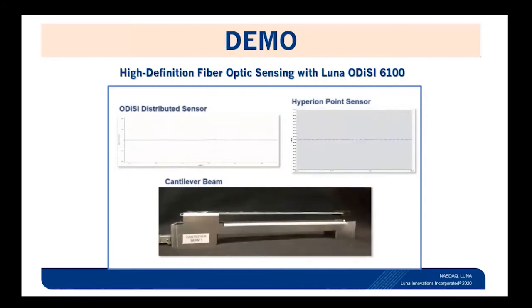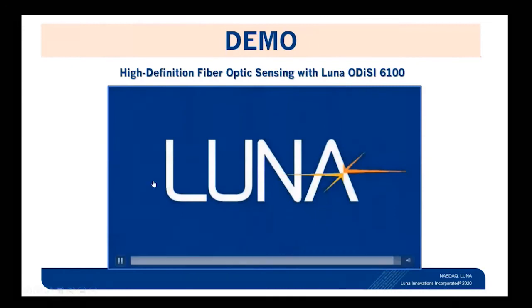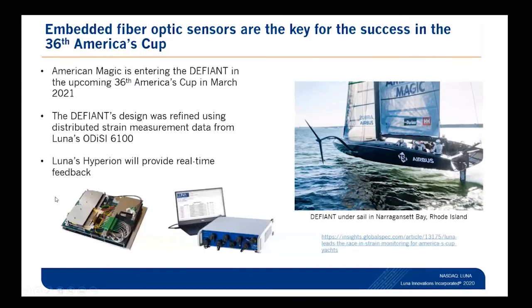And as we go through and we cycle the beam, you can see the benefits of the high-speed fiber Bragg grating on the right versus the ODiSI being able to capture the lower speed measurements on the left. So that's how you can use the two sensors together if you're going to be, let's say, using the ODiSI for determining where you're going to need to monitor when your part is put into service, and then using the Hyperion to monitor it. And one example of that we've got is on the American Magic boat.